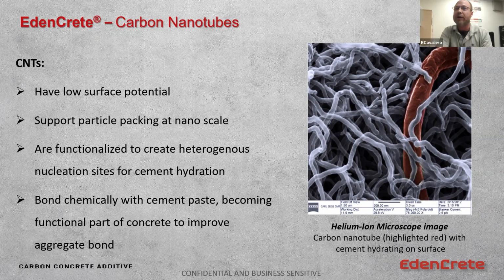And what you're looking at here on the right is a helium ion microscope image at 76,000 times magnification. And we've had our marketing group color this tube red. And what you can see is the dimpling on the surface there. And that's the cement having actually encapsulated or hydrated onto the carbon nanotube. And that provides a robustness and a safety factor, right? Those tubes are embedded, they're strong, they're a part of the hardened matrix, and it also prevents them from liberating when the concrete is demolished. A building's knocked down. Somebody kicks some EdenCrete up on the side of the road and it's been spilled, right? None of that is going to be a problem for anybody who's using the product.